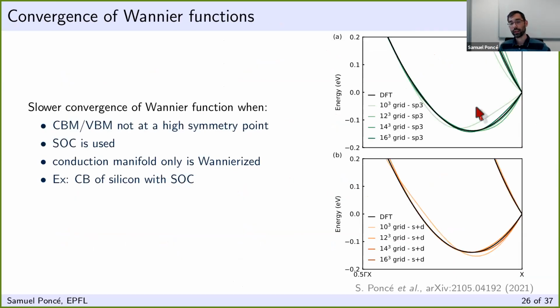The reason for that is because of the electronic Wannier functions. What I'm showing here is a zoom in, in the case of silicon, on the conduction band minimum. This is how the interpolated Wannier bands look if I'm using an sp3 projection or an s+d projection. Of course, I need to mention that this is a bit of a pathological case because the conduction band minimum is not at a high symmetry point. Therefore, it's not part of the original grid on which you ask Wannier to do the interpolation.